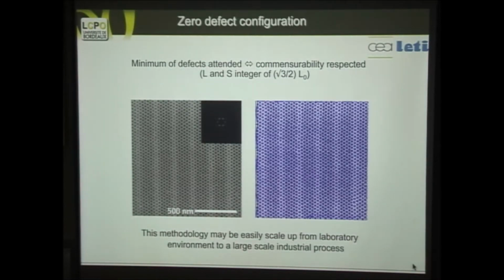So if you respect this rule, you see now that here we call it the Delaunay triangulation pattern. What we do in this pattern is see, for every spot, how many neighbors we have. Since here we have a hexagonal system, in a defect-free system every spot should have 6 neighbors. If it has 5 or 7 neighbors, that means we have a point defect. And as you can see here, we illustrate that we have no defects at all at this level.